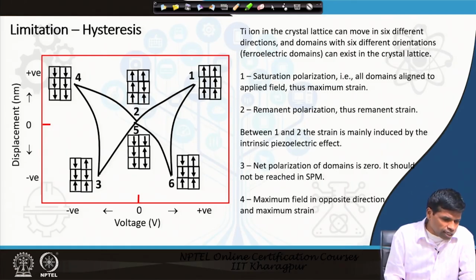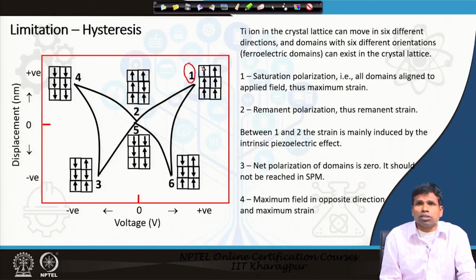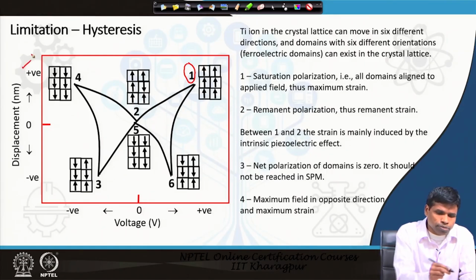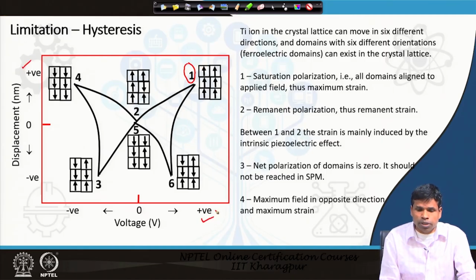For example, let us say here at position 1, we have 6 domains, all orienting in the same direction as the applied field. Therefore, displacement is maximum. Here the field is positive, displacement is high, and this is the saturation polarization. All domains align with the applied field, that's the low energy state with a maximum strain.